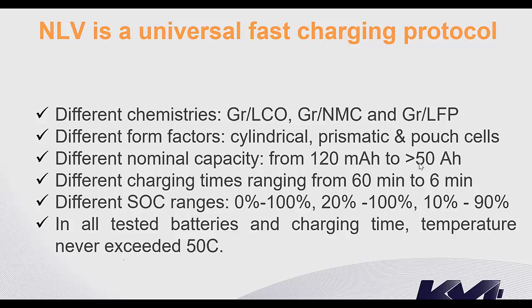And the largest battery we tested had 55 ampere hours, and very soon we will be testing 63 or 64 ampere hour cells made by a Chinese company. And the other thing is that we were able to charge batteries from 1 hour, this is the maximum time we have used, to 6 minutes. And 6 minutes today is the world record for any charging method. And we are proud actually that we have achieved that record here in Singapore.